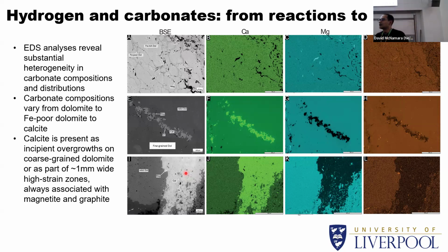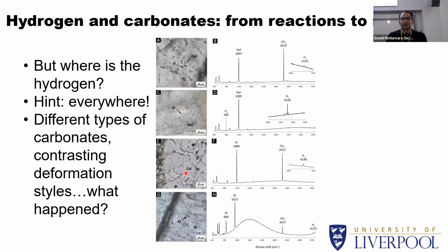If this were the case, we would need to demonstrate the presence of hydrogen. It is not an easy molecule to quantify. A lot of analytical techniques used for geochemistry don't work for hydrogen because it is super light. But if you poke around fluid inclusions with a laser and quantify the Raman shift, it works beautifully for hydrogen quantification. That is what we did. We looked at fluid inclusions in the dolomite and in the calcite, and hydrogen is present in every single fluid inclusion that you see.